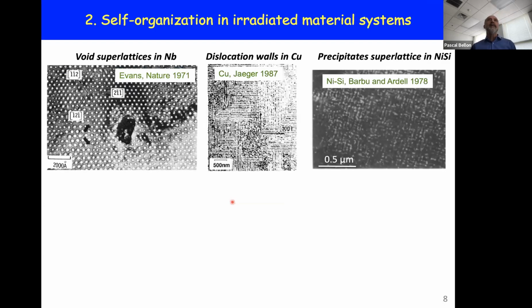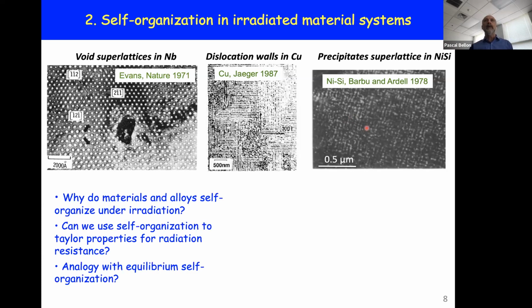So here are more examples of self-organization reactions in irradiated materials. On the left-hand side, you have a void superlattice that is formed in irradiated niobium. In the middle, you have walls of dislocation loops and dislocations that formed in pure copper under radiation. On the right-hand side, this is an alloy, which is what we are going to focus on in this presentation, of nickel and silicon. Again, silicon-rich regions form those gamma prime precipitates. And here you can see that again, there is sort of a finite size for those precipitates, and it even seems that they form an ordered array of precipitates at the scale of tens of nanometers.